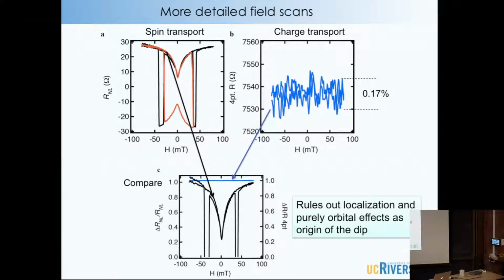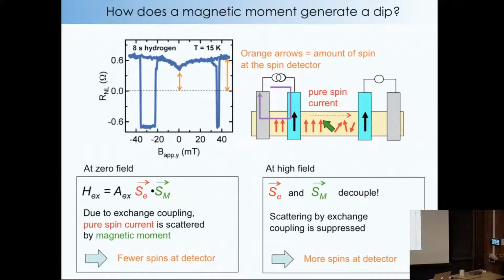Oh, this is just to show that the magnetic field dependence of resistance changes less than 0.17%, and that's just the noise level of our measurement. So the dip can get pretty big, but the resistance doesn't change at all compared to that. So this rules out localization effects purely from orbital effects. This rules that type of stuff out. Okay, and I am going to speed up a little bit.